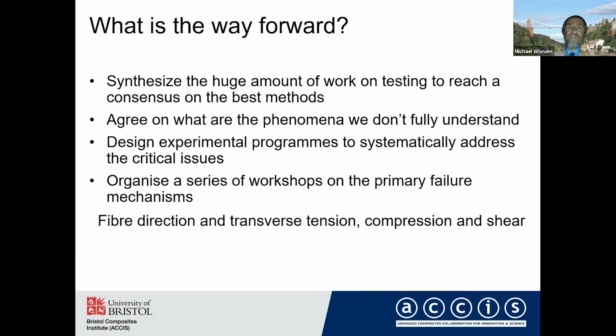We've done quite a lot of work on that, and I think we've got quite some understanding of that, and it all depends on the local failure. If you have a crack or local stress concentration, you get a very complex damage sequence around there with cracks and delaminations and localized fiber failure. And what we have to do in order to be able to predict that effect is to be able to take account of those localized damage mechanisms and the effect they have on the overall performance. So we've done a lot of modeling work on that as well as experimental work. I think it's a very interesting topic. But again, it's probably subject for a whole other talk.